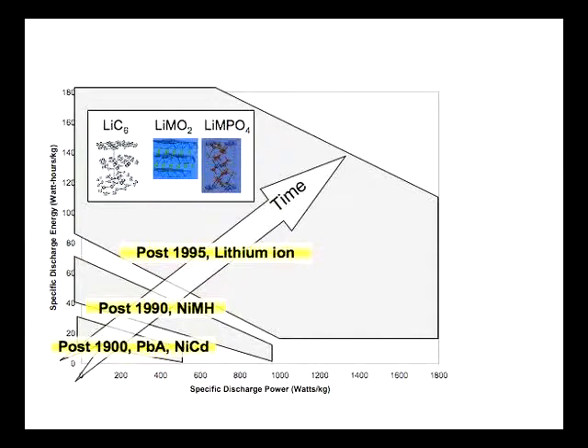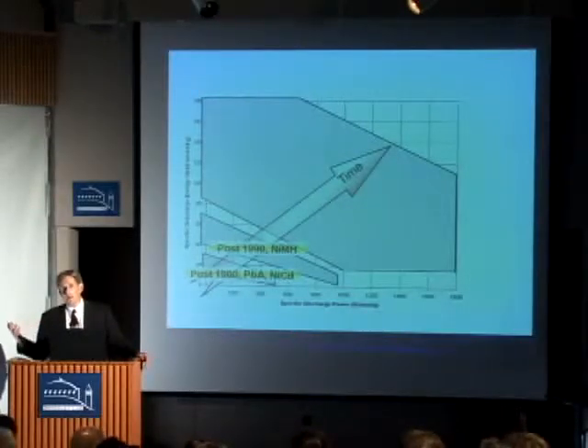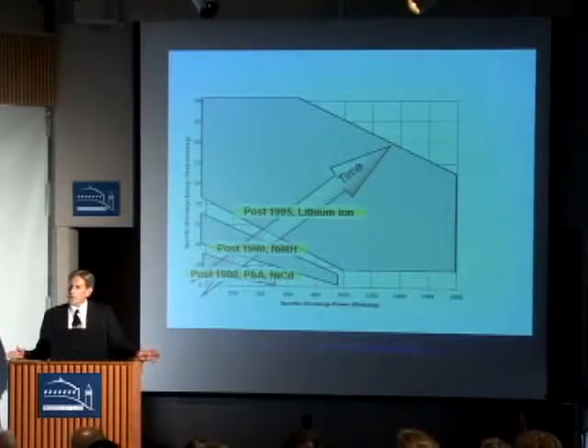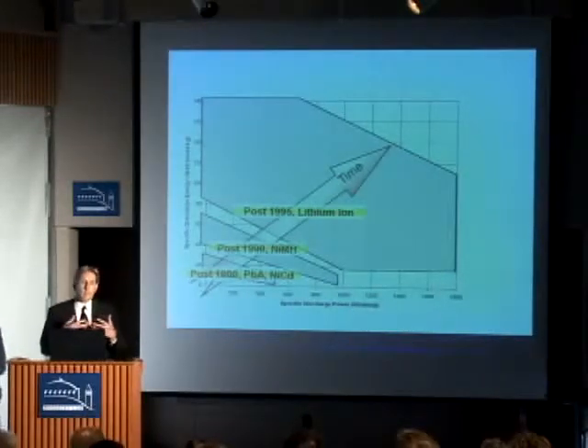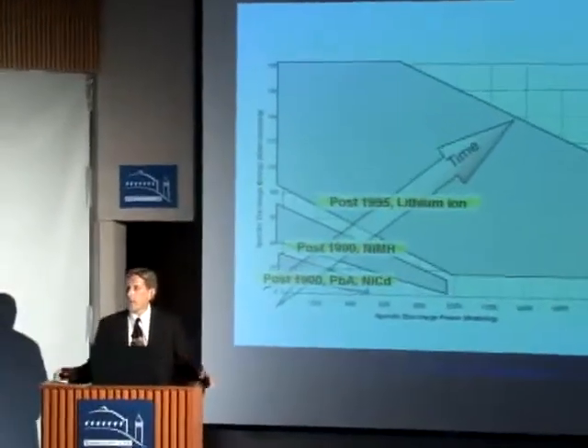What's driving lithium-ion? Before the turn of the century, lead acid was the dominant rechargeable battery and the workhorse of traction applications. Then in about 1990, insertion electrodes came out — nickel metal hydride batteries are an insertion electrode, where you're inserting hydrogen in nickel oxy-hydroxide. Shortly after, lithium-ion came out mainstream — also an insertion electrode-based system. Insertion electrodes typically have very high cycle life, controlled by solid-state diffusion. Materials research has played a dominant role, with graphite planes stacked for the negative electrode and metal oxides and metal phosphates for the positive electrodes.